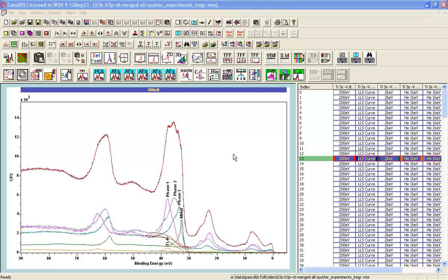So we have 5 different experiments that should produce slightly different outcomes for the spectra, and what we would like to do is understand how these outcomes differ in terms of shapes that we can identify within the data. The 5 shapes that we have found within the data represent 5 different phases of the oxide. In fact, it's 4 oxides and 1 metal, and these shapes are fitted to each of the spectra in a